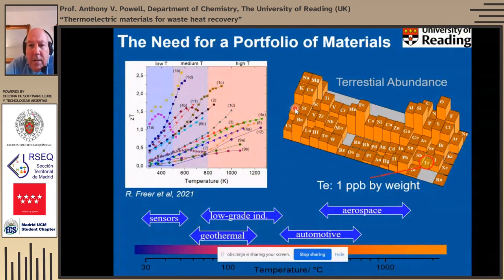A further constraint that we have is really on the actual component elements themselves. So most high-performance thermoelectrics to date, including bismuth telluride, have appreciable quantities of tellurium in them. So bismuth telluride down at ambient type temperatures, lead telluride at higher temperatures. The abundance of tellurium in the Earth's crust is about 1 part per billion, which is about the same as gold, for instance.